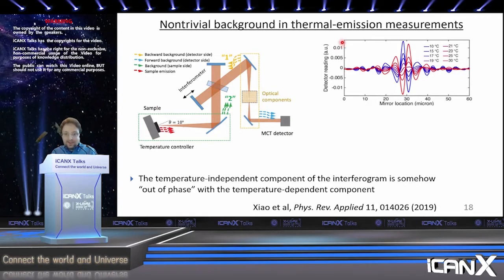What we did here is measure the interferogram as a function of different temperatures, both above the temperature of this weird transition point and below. At 30 degrees and at 10 degrees, you might remember that the signal that we measured was actually quite similar. The spectrum was at similar intensity at 30 degrees and at 10 degrees, which is very strange. We see that in the interferogram as well, where the intensity is about the same, but notice that the interferogram looks pretty much out of phase between 10 degrees Celsius and 30 degrees Celsius. So this was quite interesting, that something was going on there. It's a suspicious situation.